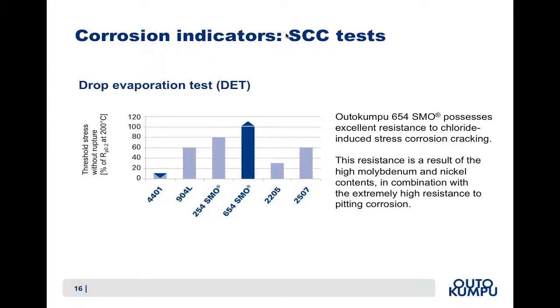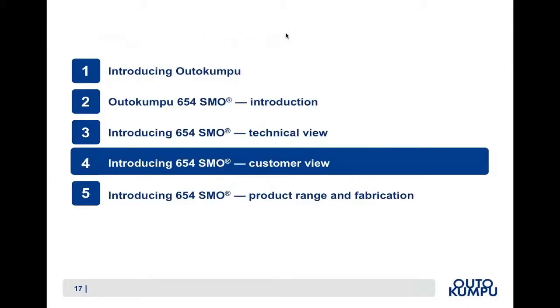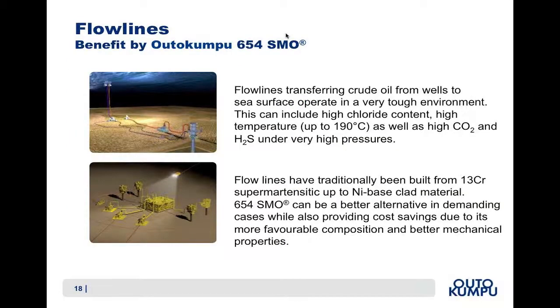Looking at other stress corrosion tests, we can see that Outokumpu 654 SMO is superior or on a par with the other stainless steels or nickel-based alloys. Turning away from the technical aspects, let's now look at some customer views of this remarkable alloy, where it's been used as an alternative to the other grades or indeed nickel-based alloys. And on this slide, you can see an example of where it's been used in flow lines which transfer crude oil from offshore wells to the surface of the sea.